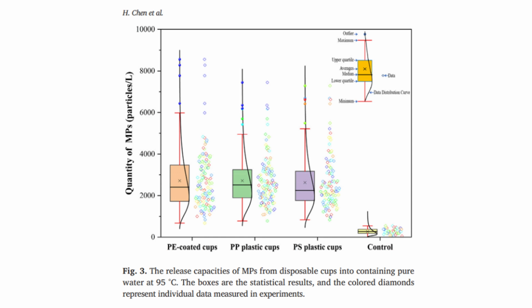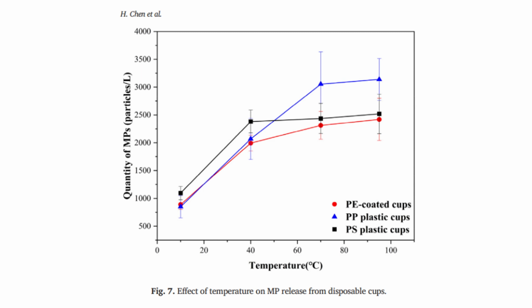As shown in Figure 3, the microplastic release from the disposable cups is significantly higher quantity than that of the control blank samples. There is no significant difference in the microplastic particle count among the 3 types of tested disposable cups. Elevated temperature clearly intensifies the release of microplastics from the disposable cups, as can be seen here. Polyethylene-coated paper cups are typically recommended for hot takeout beverages over plastic disposable cups, but they do not appear to release fewer plastic particles compared to those plastic cups. So there you have more evidence on disposable paper cups.